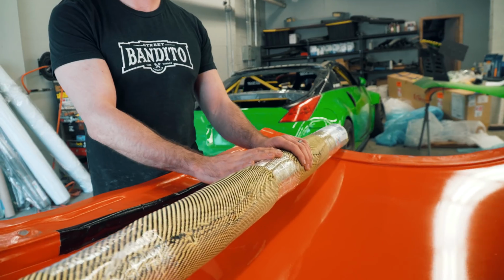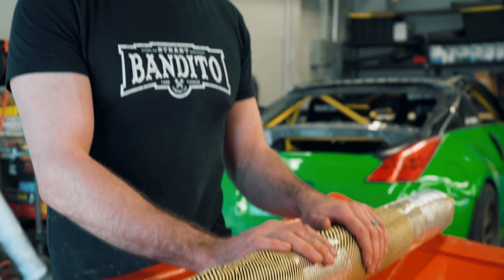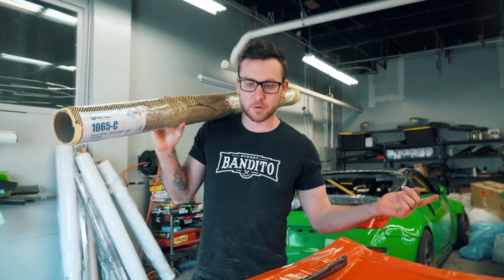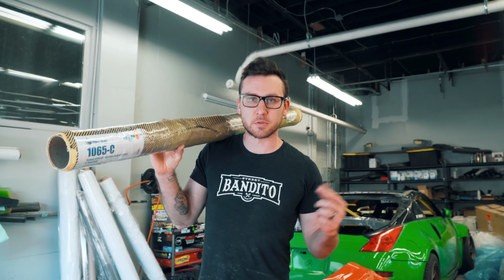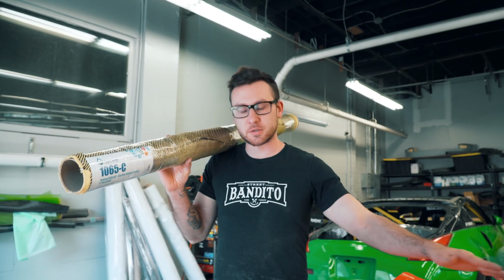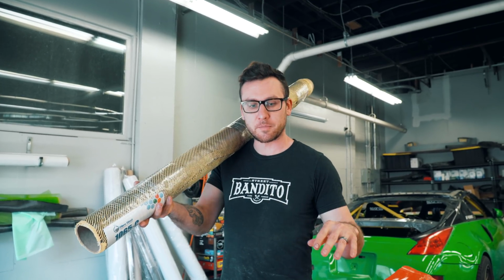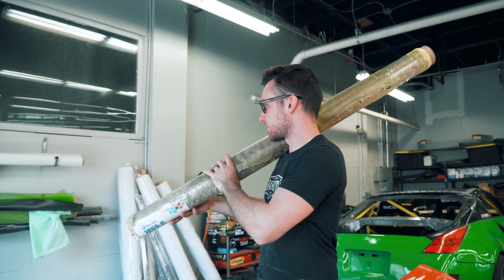There's so many ways to do this. Yeah. But, like you said, it's more than one way to skin a cat. Yep. So we're gonna start by just laying in some resin here. We're laying our first layer of Kevlar, and then just keep going. Do another layer of carbon, Kevlar. Make sure it doesn't have too much resin in it. Any excess resin will get pulled out into the bleeder ply stuff and thrown away. But so Kevlar, 2 carbons, another Kevlar, the same.